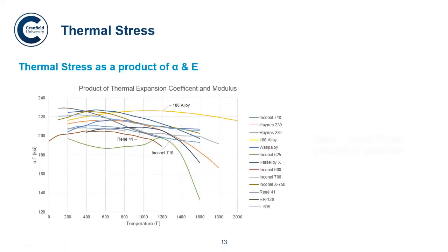So we also looked at the thermal stress, which we defined as a product of the coefficient of thermal expansion and the elastic modulus. We did prefer a lower thermal stress for the application. As you can see, 188 comes out really quite high throughout the temperature range. And then you've got Rene 41 and 718 kind of in the middle, and they swap places again when they get to higher temperatures. Another interesting alloy to look at in this comparison is Inconel 625 as well, which has a very interesting pattern.